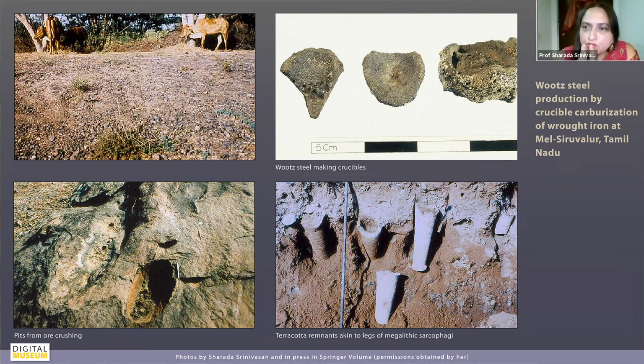of the steel. So the wrought iron was being kept in these crucibles along with carbonaceous material, which was fired in very long firing cycles at very high temperatures, getting carburized to steel. And at the bottom, you also see some remnants at Melsirivalu of the legs of megalithic sarcophagi, because the site shows some traces also of megalithic occupation.